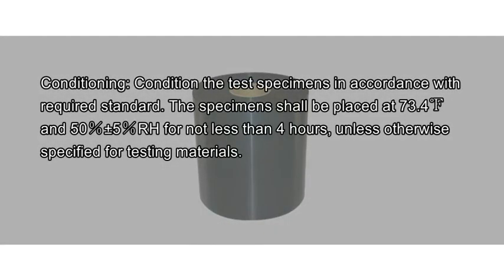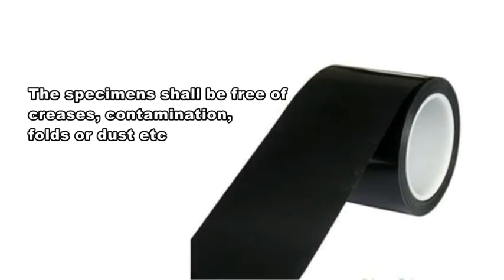Conditioning. Condition the test specimens in accordance with the required standard. The specimen shall be placed at 23 plus or minus 2 degrees centigrade, that is, 73.4 plus or minus 3.6 degrees Fahrenheit, and 50 plus or minus 5% relative humidity for no less than 4 hours, unless otherwise specified for the testing materials. Specimen selection.